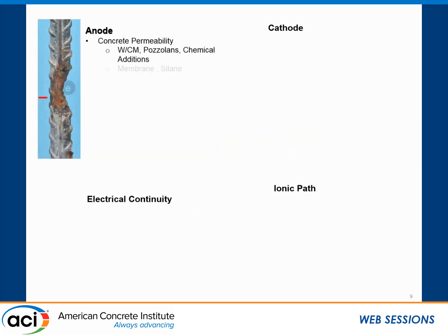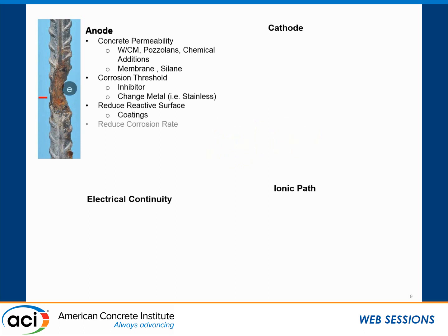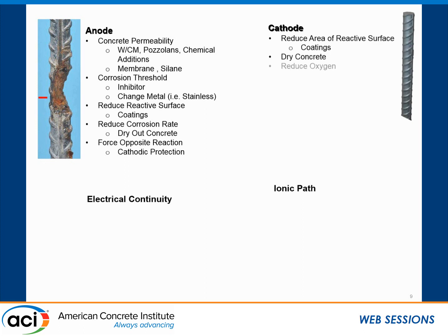We can do different things at different points. For the anode, we can affect the concrete permeability, changing the water cementitious material ratio through pozzolans and chemical additions. We can change the corrosion threshold through inhibitors. We can reduce the reactive surface, like with coatings. We can force the opposite reaction with cathodic protection. At the cathode, we don't really see a whole lot of things happen, but it's still an essential part of the corrosion cell.